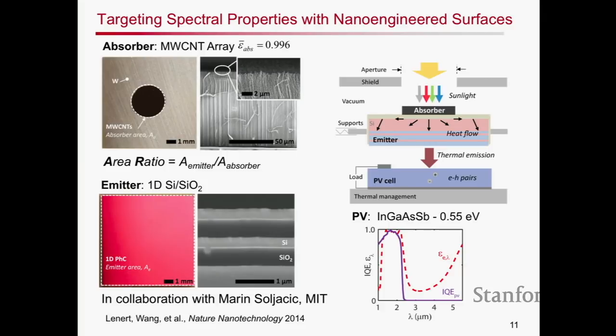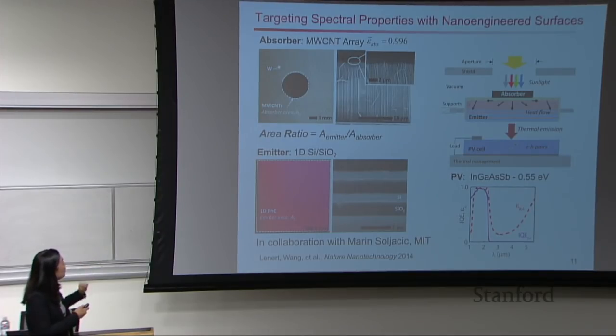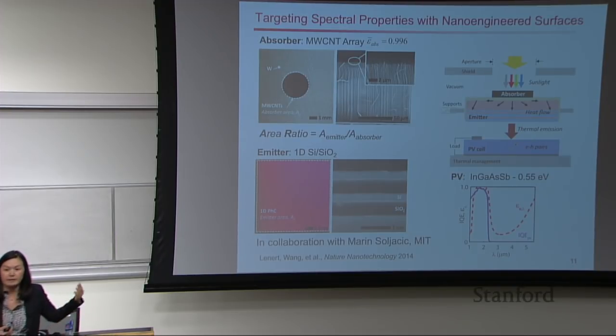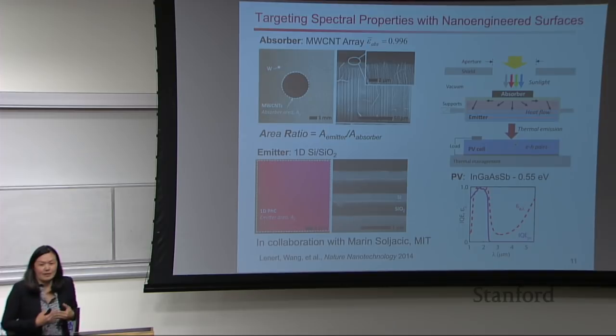So we've taken what we've defined as an area ratio, where we pattern a certain area with carbon nanotubes, such that we can have a relative area, a ratio of the area of the absorber to that of the emitter. What we've done here is selectively pattern this such that we can increase the amount of irradiance, the amount of sunlight onto this absorber, so that it can essentially overcome the emissive losses in this case.